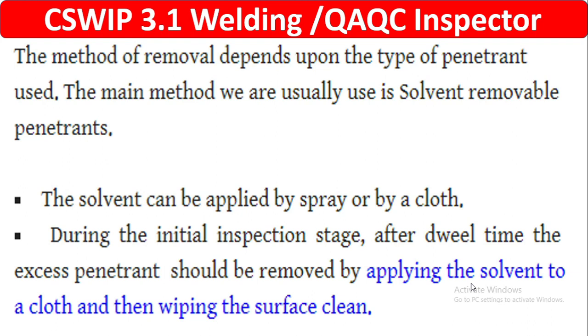The method of removal depends on the type of penetrant used. The main method is solvent removal — the solvent can be applied by spray or by cloth. During the initial inspection stage after dwell time, the excess penetrant should be removed by applying solvent to a cloth and then wiping the surface clean. So option C — wipe clean using a lint-free cloth soaked in solvent remover — is the correct answer.